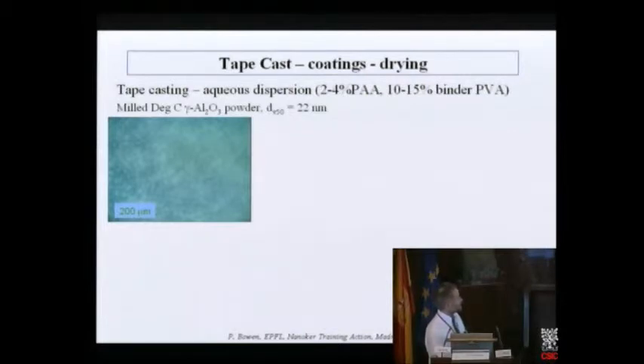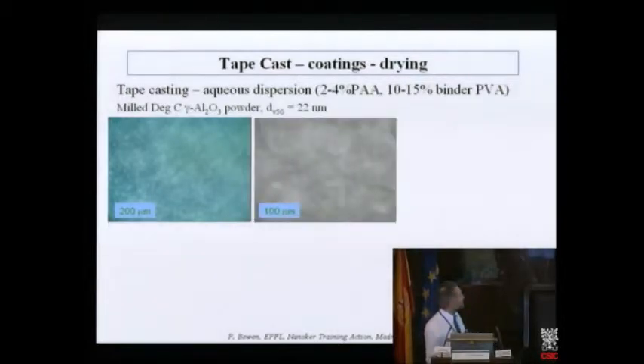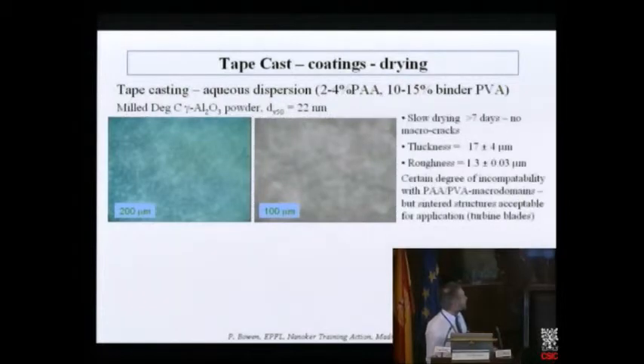You use 2 to 4% of polyacrylic acid dispersant, 10 to 15% of polyvinyl alcohol. So this then becomes the question. We can formulate it. We can put in a lot. We can stop macro cracks. We can get film thicknesses of 17 microns, which is what we were trying to do in this particular case. It's just then a question of, is this okay for your application?